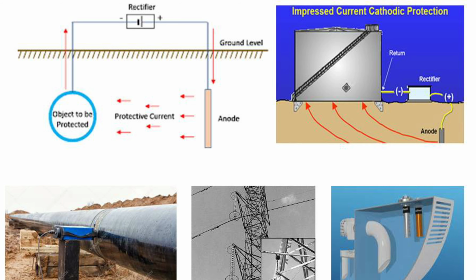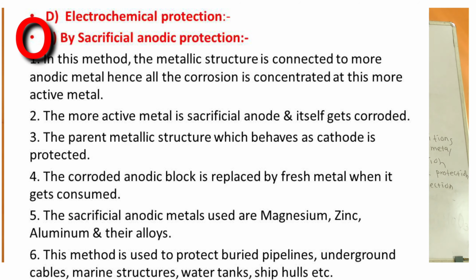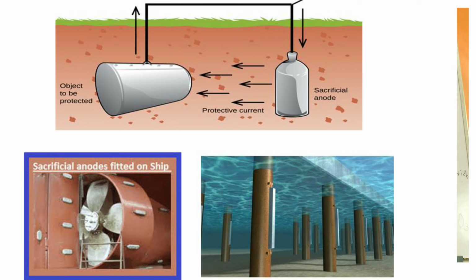Then the second way of electrochemical protection is sacrificial anodic protection. In this protection method, the metallic structure to be protected is connected by wire to a more anodic metal. Hence, all corrosion is concentrated at this more active metal. The more active metal itself gets corroded slowly. The parent metallic structure, which behaves as cathodic, is protected. The more active metal which is used is known as the sacrificial anode. It gets replaced when it is corroded. For example, magnesium, zinc, aluminum and their alloys. Applications of sacrificial anodic protection are buried pipelines, underground cables, marine structures, etc.